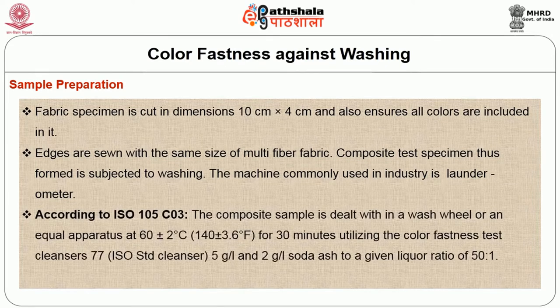As per the ISO 105 C03 standard, the composite sample is treated in a wash wheel or equivalent apparatus at 60 plus or minus 2 degrees Celsius for 30 minutes, using the color fastness test detergent following ISO 77 standards, in the composition of 5 grams per liter, and 2 grams per liter soda ash, at a liquor ratio of 50:1.